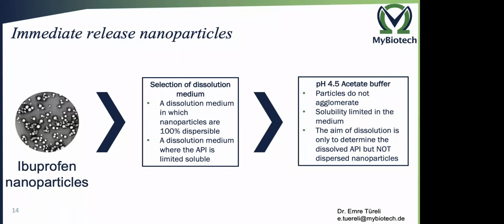For that, we prepared ibuprofen nanoparticles. For the dissolution medium, we looked for a medium first in which our nanoparticles are 100% dispersible, so there's no change in particle size and no agglomeration in the medium. And we were looking for a medium where the API is only limitedly soluble so that we can see the differences between different nanoparticle formulations. The medium we found at the end was pH 4.5 acetate buffer, in which we didn't have any particle agglomeration.